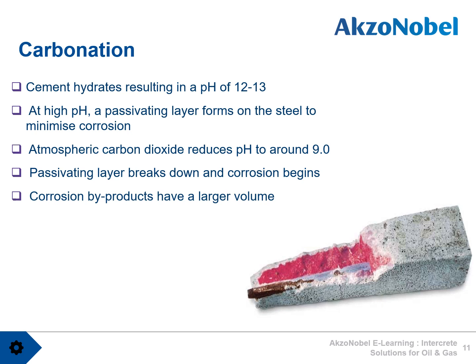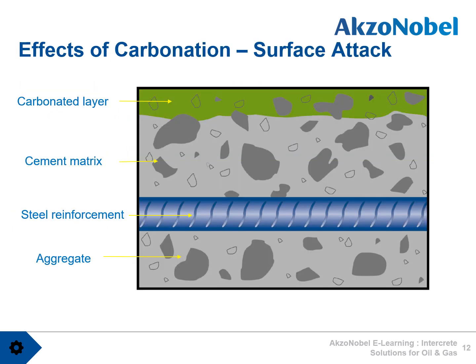Corrosion byproducts have a larger volume than the steel itself. Therefore, they expand, and this results in concrete spalling. The next two slides will demonstrate that. So here we see the reinforced concrete in section. The surface of the concrete carbonates almost immediately, and the carbonation depth will increase faster or slower due to the porosity of the concrete and the variability of the strength and quality. The more porous the concrete, the quicker the ingress towards the steel.